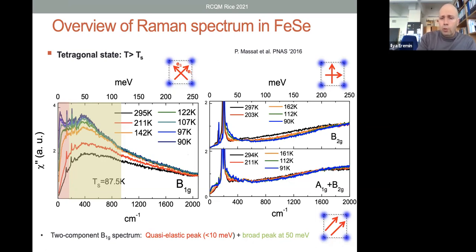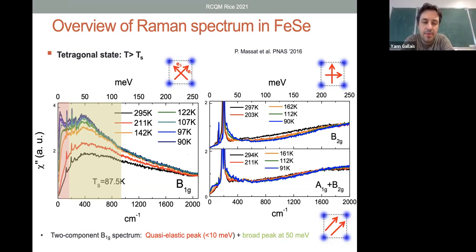But what I can tell you, for example, is that in the 122 systems, if I compare barium-122 with cobalt doped strontium-122, and I study samples that have the same TS, the cobalt doped strontium 1-2 would have a residual resistivity that is much higher, so maybe much more disorder. TS minus T naught is virtually identical.